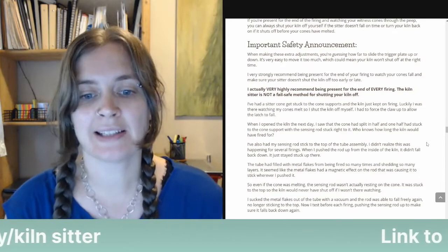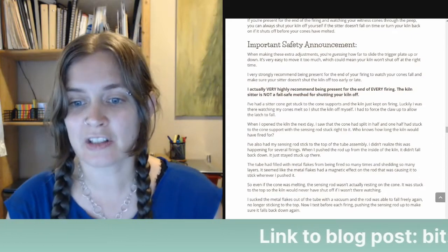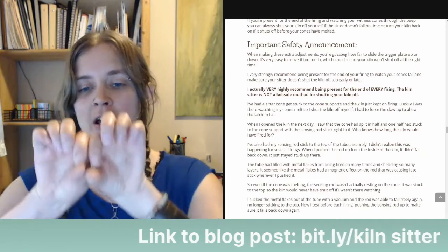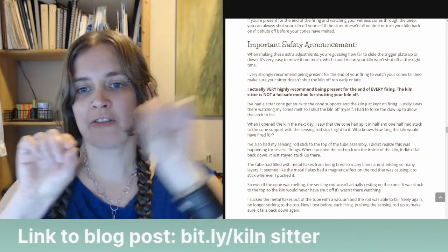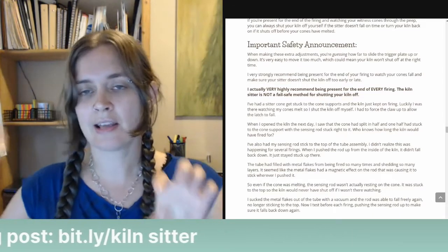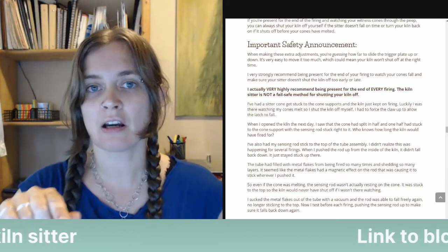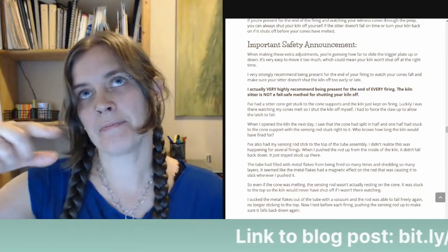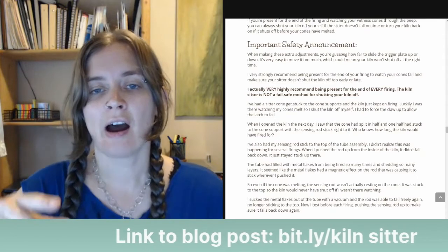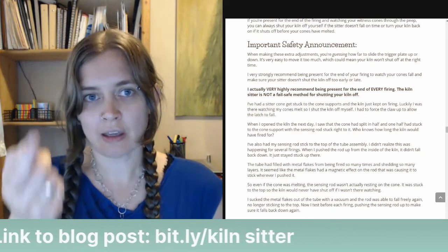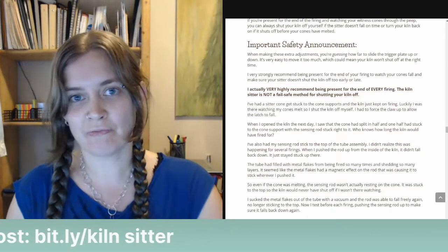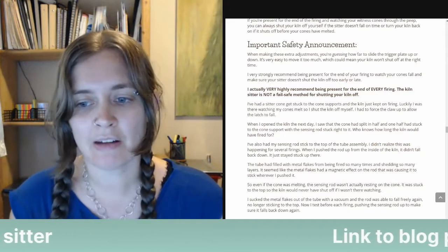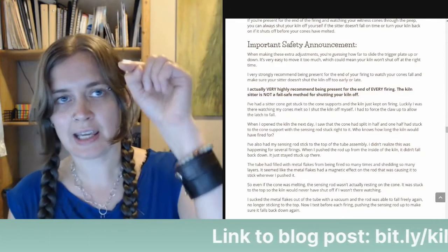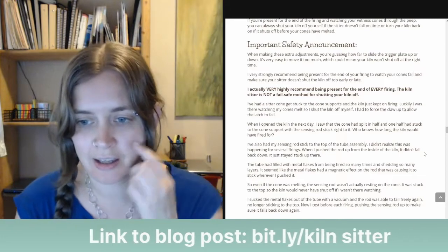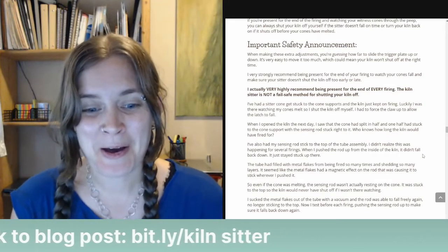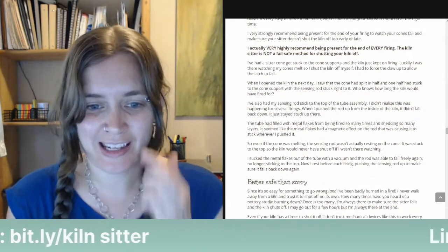I've also had my sensing rod stick to the top of the tube assembly. So you've got your tube assembly that goes from the inside to the outside of the kiln, and the sensing rod goes down the center. When the kiln is off, if you flick the sensing rod up, it should just fall back down. What I found out was that it was just sticking up and it wasn't falling down. So my kiln wouldn't have shut off then either.